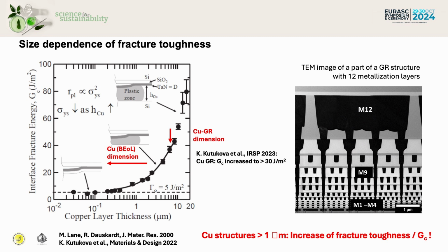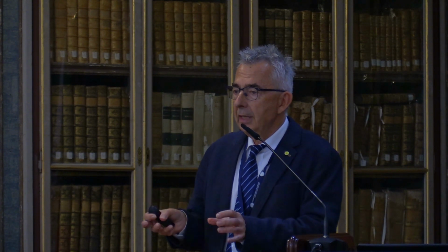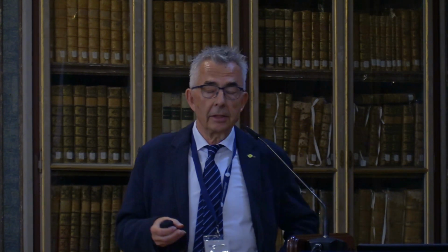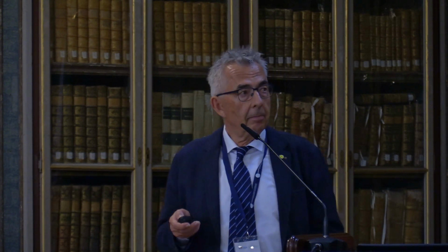It's about 2 microns. You see it's already a bit plastic. But the guard ring structures, which I talked about, which is a particular structure in the chip, have about 8 microns. And with these 8 microns, it is possible to stop the crack propagation.